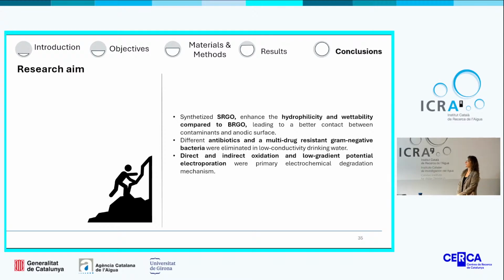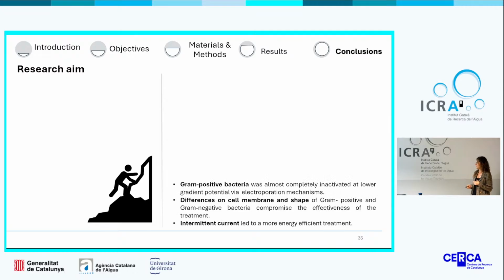In the second chapter, the synthesis of sulfur-reduced graphene oxide enhanced the hydrophilicity and wettability compared to previously synthesized boron-reduced graphene oxide, leading to a better contact between the contaminants and the anodic surface. And different antibiotics and multidrug-resistant bacteria were successfully eliminated through direct and indirect oxidation in low conductivity electrolytes.